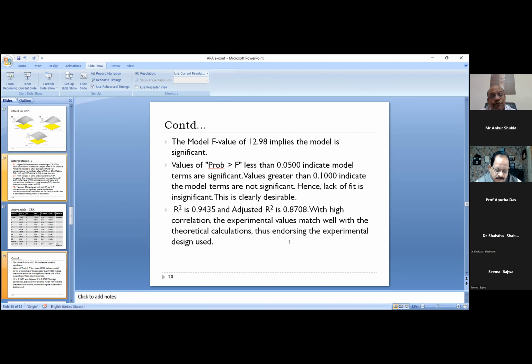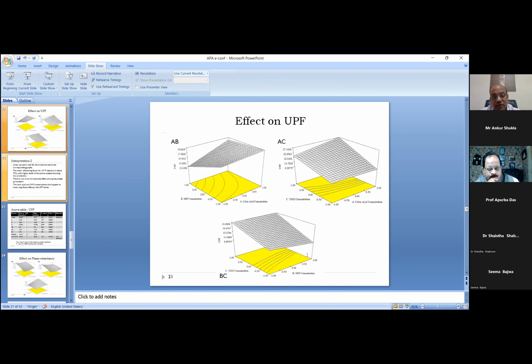So the model F value 12.98 implies that the model is significant, and the P value I've already told. And the R square value, the correlation is very high. That is why you are getting a very high R square value, that is 0.94. So the correlation between the actual experimental results and the calculated values by this experimental design, they have a very strong correlation. So that further endorses the validity of the experiments which are carried out.